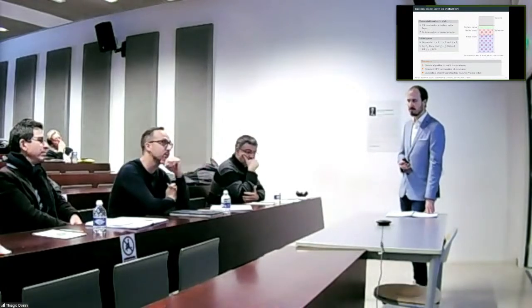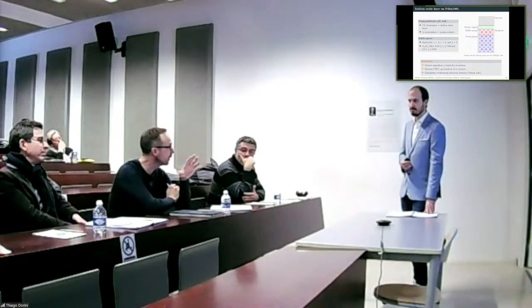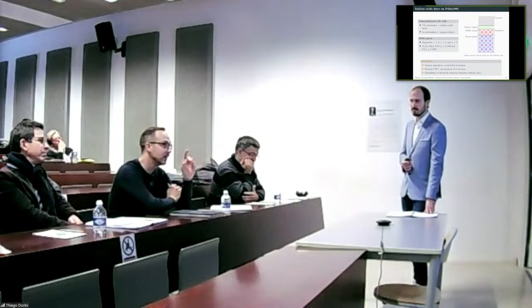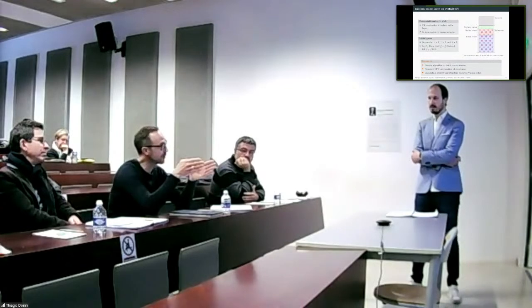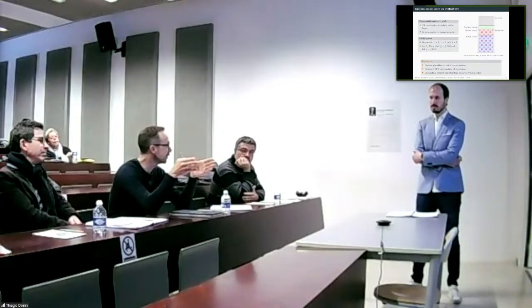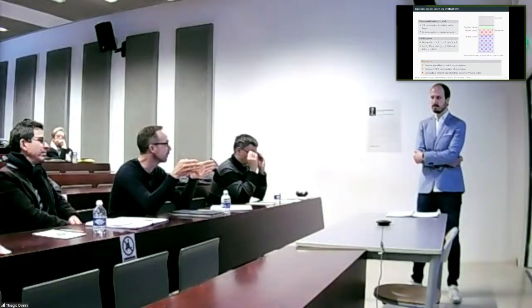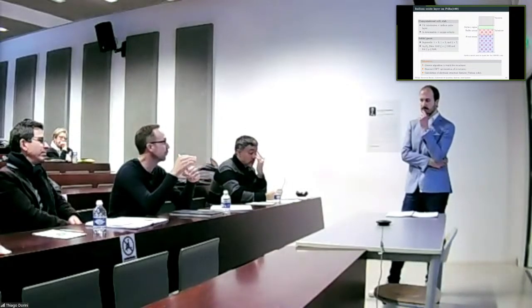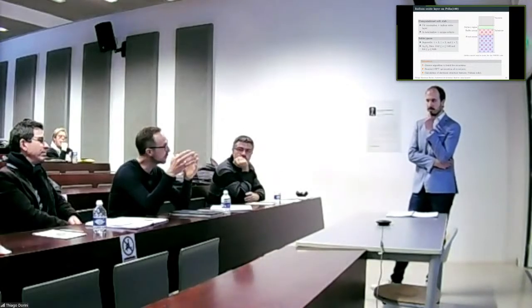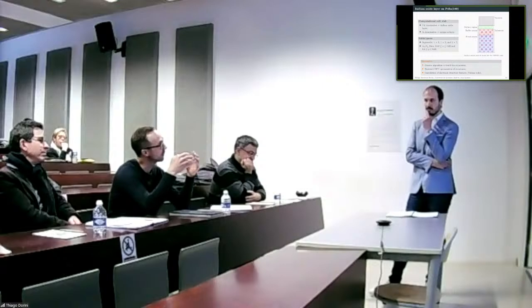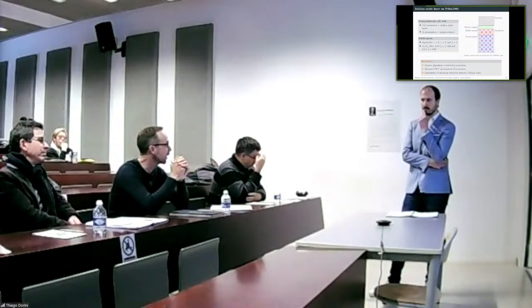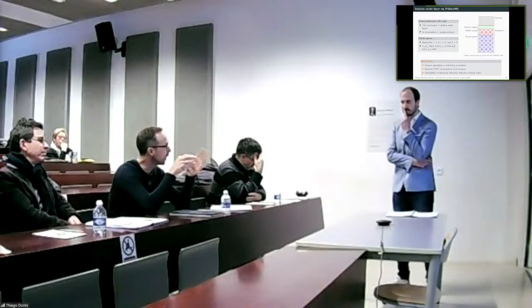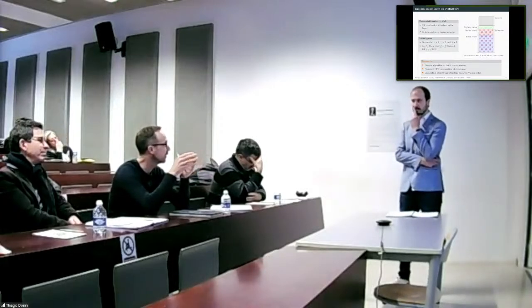You have started here in the presentation also with a nice plot showing that the rumpling is intimately linked to the charge transfer in the system. And of course, if we now force the honeycomb to be a 2x2 on platinum, where it wants to be 2.15 times 2.15 in the experimental system, we maybe induce some rumpling into the system which is not present in real life. And then maybe we overestimate the adhesion energy in the honeycomb, which makes it come out as a favorable system as compared to the approximant model. Can you argue a little bit how much these effects are?